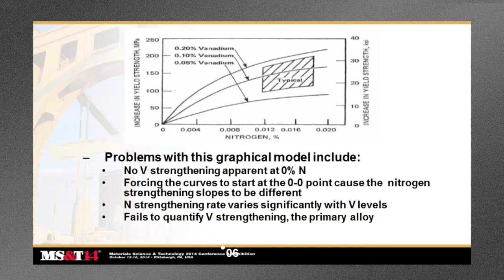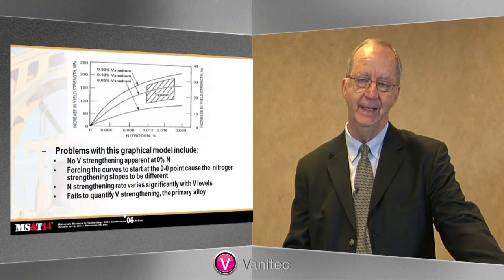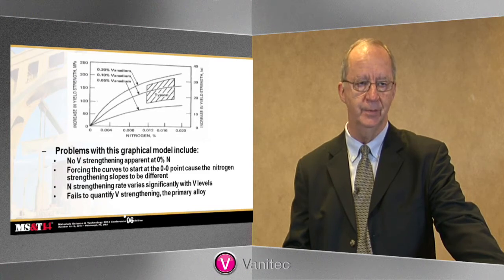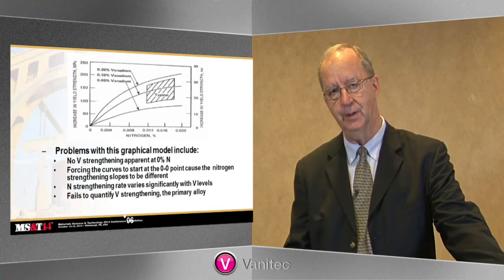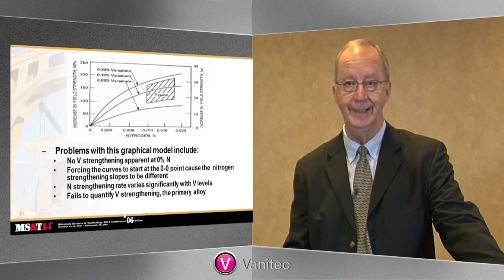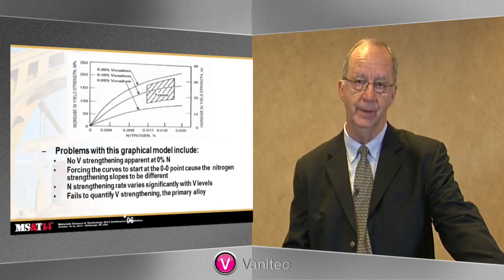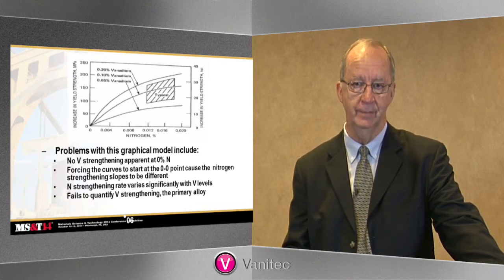And forcing these curves to start at the 0 point causes the nitrogen strengthening slopes to be considerably different depending on the vanadium level. The nitrogen strengthening rate, therefore, varies significantly at these different levels, which isn't necessarily consistent with what subsequent research has shown. And it also fails to quantify vanadium strengthening, which is the primary alloy being used by the metallurgist in their alloy design. They need to know how much vanadium do I need to get to the strength that I want. And it's difficult to tell from this curve simply because vanadium content is not one of the variables of the graph.